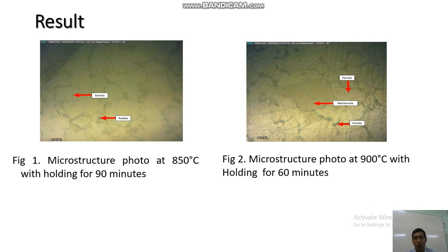The microstructure for the carburizing process at 850 Celsius degrees with a 90-minute holding time: the pearlite structure formed in grain boundaries is increasingly dominant. However, from the result obtained, the hardness values increase. The photo microstructure.